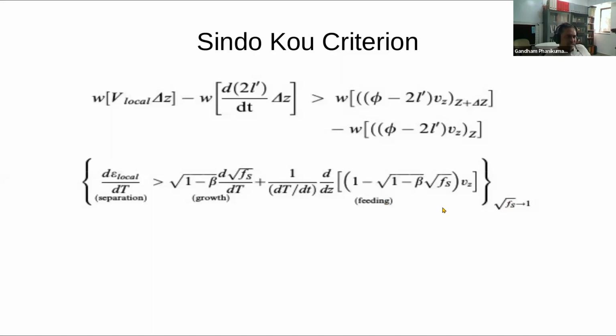From this equation, what we can say is, if you have this particular term very low, that means the right hand side is low, and therefore the left hand side is likely to be higher. Or you can also play with the cooling rate. If the cooling rate is slightly higher, then because it is coming in the denominator, this term will become smaller, and that also will help you. So either you choose the alloy such that the last to solidify solid is over a small range of temperature, or you have a slightly higher cooling rate. They both give you the same effect.